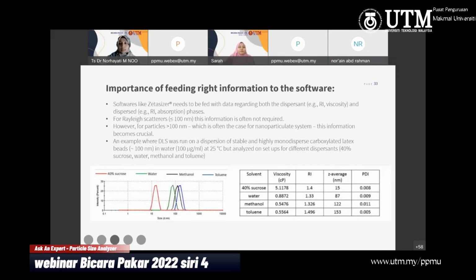This is another thing that I want to give you information about: the viscosity of the diluent, the one you use for diluting your sample. Some use sucrose, water, methanol, toluene, so they have different viscosity. With the same sample formulations, if you do dilutions with different diluents, you can see the size is different. By using 40% sucrose, you get only about 15 nanometers, but if you use toluene, it gives you 153, so you can see that it's quite big, a broader size. If you give the wrong information when you send your samples, if you didn't mention this in your form, you still get the results, but your result is not correct.